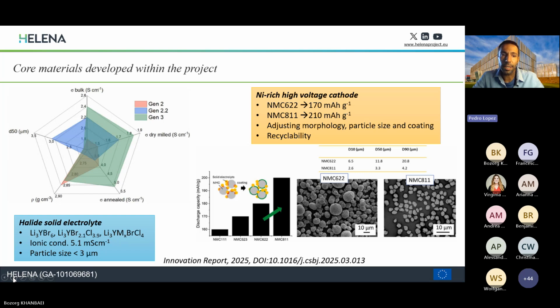On the same side, the active material has also been developed within the project, targeting two different nickel-rich high-voltage NMC cathodes. We started with the NMC 622, with a capacity of 170 milliampere hours per gram, and now we are progressing towards the NMC 811, which delivers a higher energy density. Again, in this case, we have adjusted the morphology of the active material as well as the particle size and the coating, with a focus also on the recyclability of this NMC material, having high added value of transition metals in its structure. If you could move to the next slide.